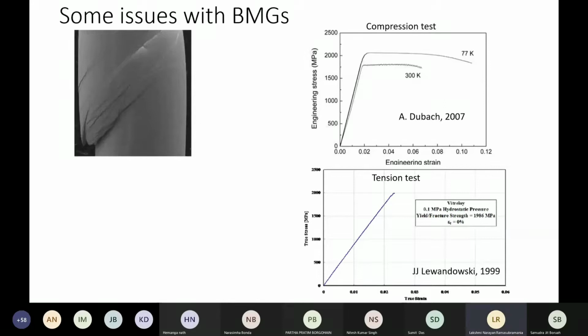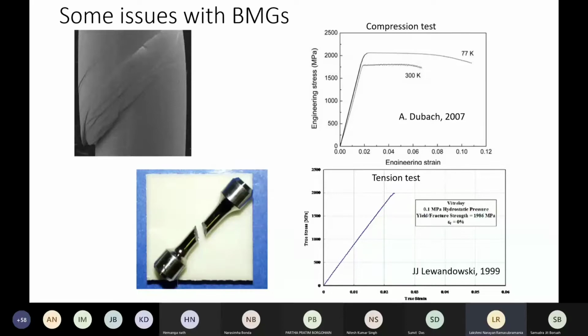But when I do a tension test, the material does not show anything beyond the yield stress. Again, you see that the elastic portion goes up to 2000 MPa. But after that, the material fails. You don't see any ductility. And that is what we also see: some kind of a brittle failure. So this material appears to have plastic deformation only during compression and not during tension.